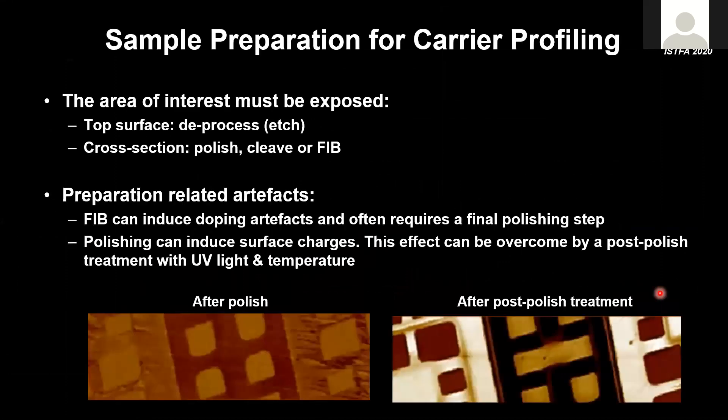A few practical aspects: very often these measurements require access to the area of interest, since most AFM methods measure what's directly below the tip — they are surface techniques. This often involves etching steps, top-surface access, or cross-sectioning. Different cross-section methods like polishing, cleaving, and focused ion beam are all valid, but when using focused ion beam, we need to be careful because it can induce doping artifacts — redistribution of the doping concentration we're trying to measure.